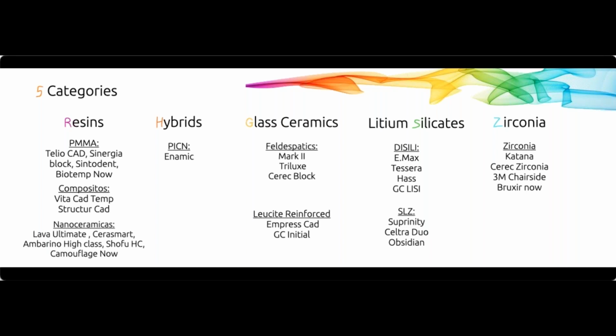And then you have zirconia, a material that is completely different from many others. The adhesion part of it is a little bit less than the glass ceramics, although some studies are coming out saying that how it bonds to adhesive systems and resin cement is as good as other glass ceramics, which is interesting. But I have one big negative thing about zirconia. Many people use zirconia because many labs started selling cheap zirconia, like $50 a crown, $99 from Glidewell, and the hammer test and things like that. Many people moved into zirconia because the other categories were breaking on them. And the reality is that the other categories are breaking on you because you're not prepping and bonding correctly.